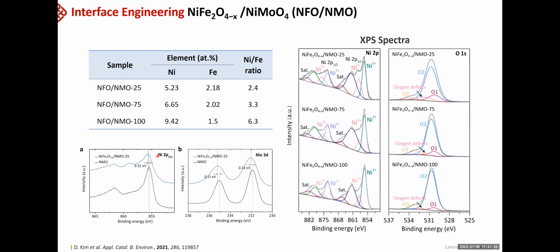Also, the nickel 2p XPS spectra show that the nickel 2+ and 3+ species show positive shifts from the initial nickel molybdate species. And even the molybdenum also shows the same kind of peak shift, which means that by forming the interface between these two, we actually make them interact quite strongly.